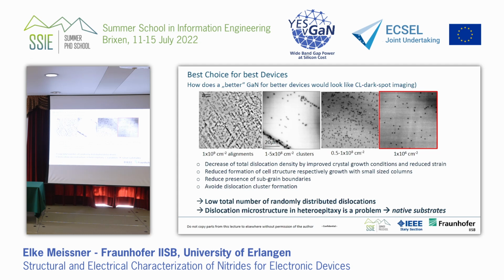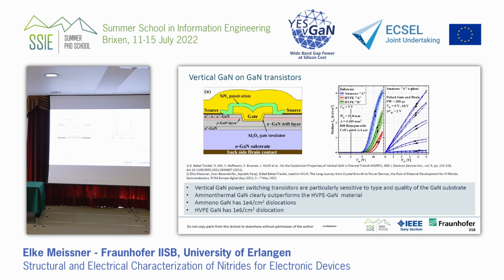So this is the consequence, how it should be, how a better gallium nitride should look. I think this red frame says everything. And how would it look? You can see it here. This is an example for vertical gallium nitride power switching transistor. And they are particularly sensitive to the type and quality of the gallium nitride substrate. And you see that they are, for example, first of all, they are much better than the ones compared to gallium nitride on silicon, and also they are vertical.